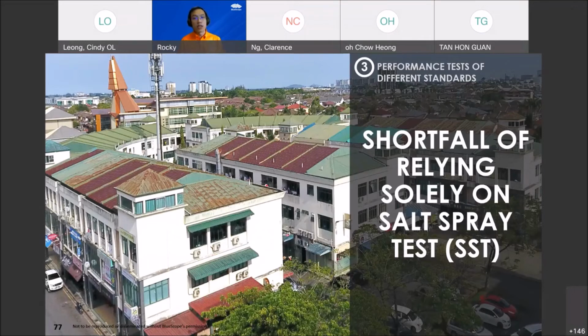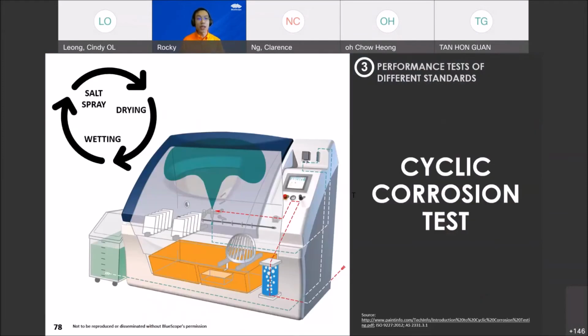Okay, on the other hand, I wouldn't say totally different from salt spray tests would be cyclic corrosion tests. Cyclic corrosion test employs a certain level of salt spray, as you can see from the cycle. It also employs what they call a drying cycle and a wetting cycle, where it will expose the samples to not just salt spray, but it will dry up the sample, and then also a wetting cycle. Okay, and consistently, I wouldn't say always consistent, but again, compared to salt spray,